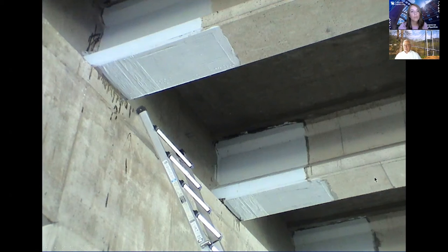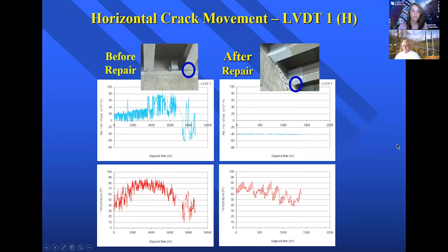And when we did that, we also monitored it for another 3 years to see what's happening. What we found out is that on the left side in here, the crack was moving quite a bit before we retrofitted it. After we did the retrofit, the crack is barely moving in here. So the repair was successful. But even to this day, we have not seen any cracks go beyond where the fabric was repaired. So for less than $200,000, we were able to repair 120 locations on that bridge and really saved at least a couple of million for the other alternative.